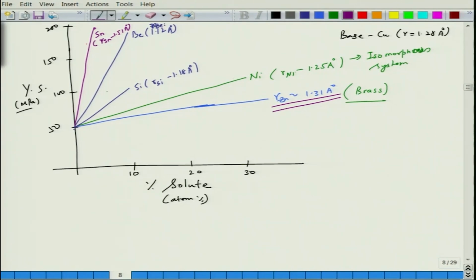When you add nickel. Silicon, again, has a smaller size than copper. So silicon increases the strength to about 100 megapascal up to about 10%. You can add beryllium, which can increase the strength again to more than 150 megapascals, for small amounts, about 10%. And then tin, you do not have to add even 10%. Tin goes all the way up to about 170, 180, maybe 200 megapascals.